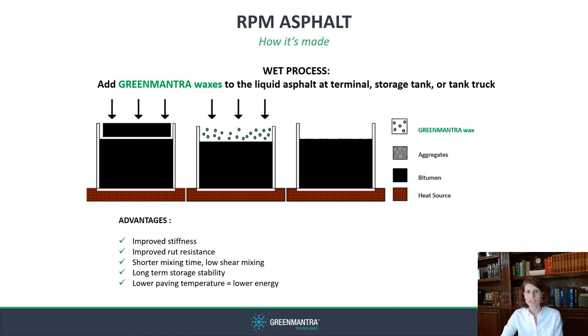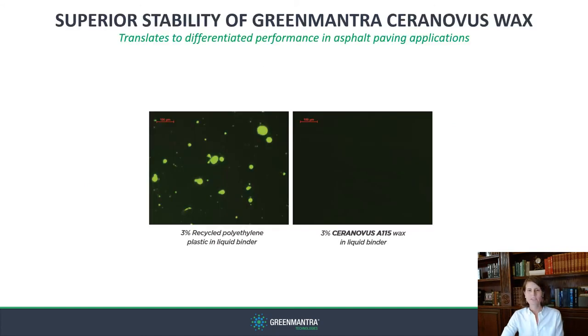The difference between Green Mantra's recycled plastic waxes and unmodified recycled plastic can be visualized using fluorescence microscopy, or FM. FM is a scientific method that uses a UV light to analyze the miscibility of components and is often used to check the distribution of polymers in bitumen. Undispersed agglomerated plastic particles appear light green in the dark bitumen. This slide shows some FM studies performed by the National Center for Asphalt Technology.